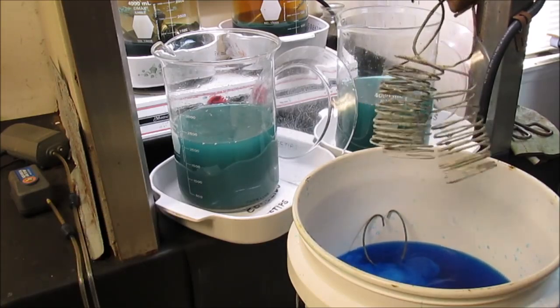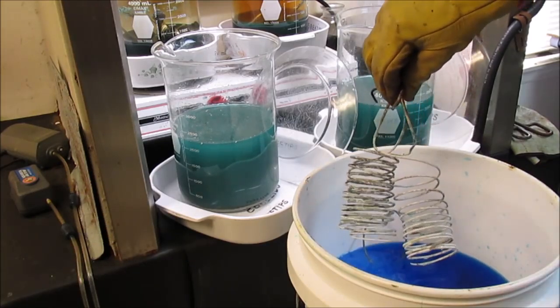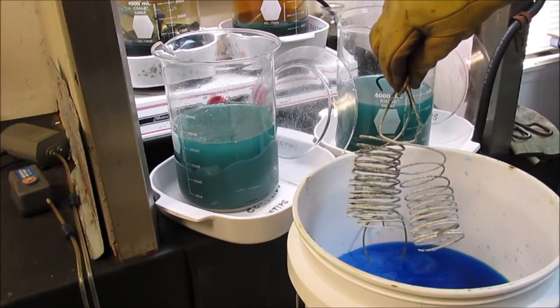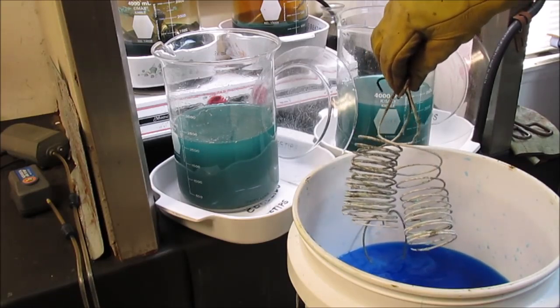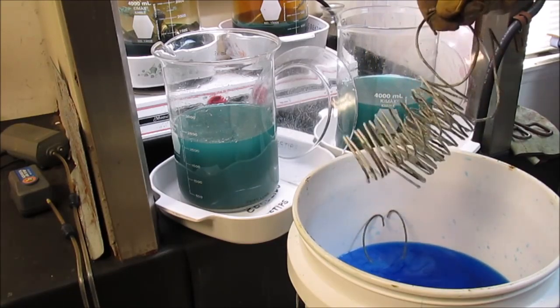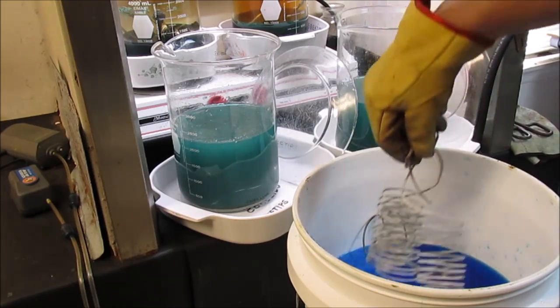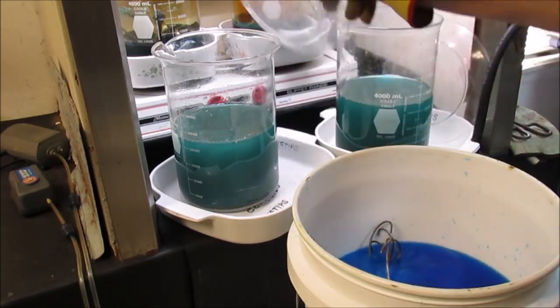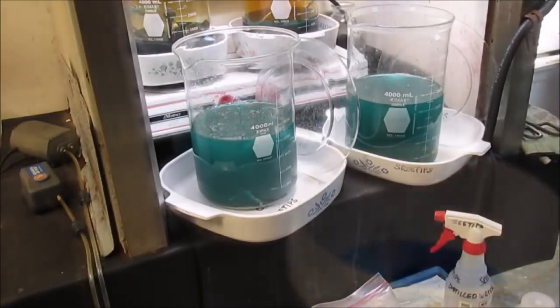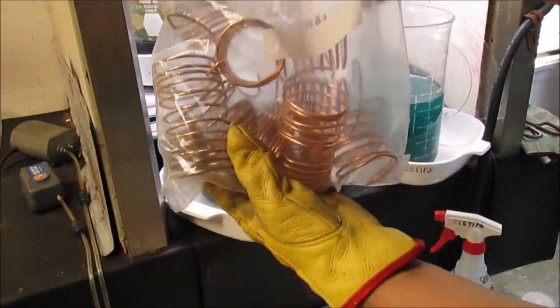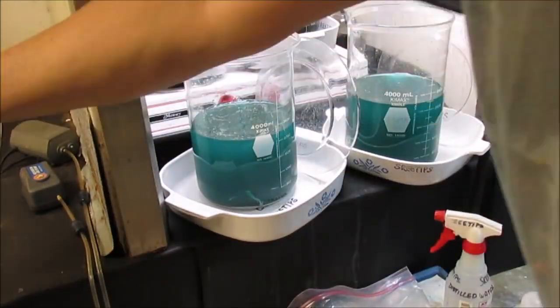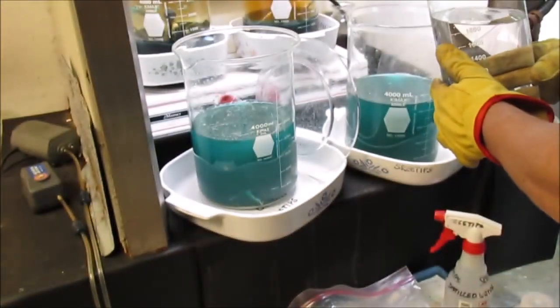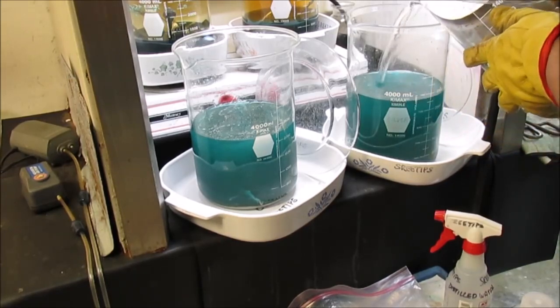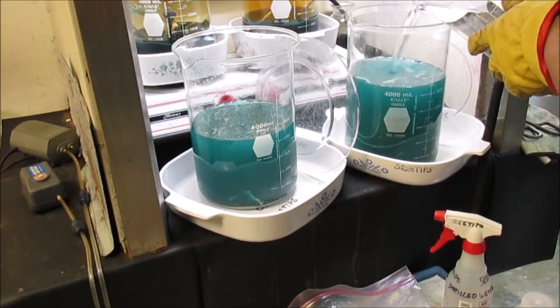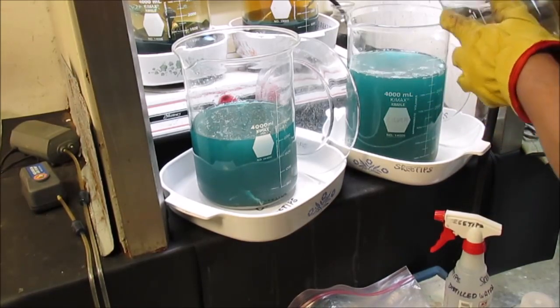See how white that is? That's a heavy passive layer of silver on there, so that the silver nitrate solution can't contact the copper and cement out. So I'm just going to throw this in my waste bucket and start over. Now I've got some fresh copper coils here. I've got some more distilled water. I'm going to dilute this down a little further to see if we can get this to start cementing out properly.